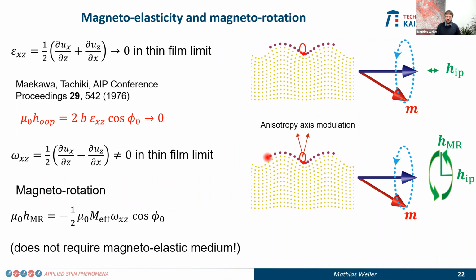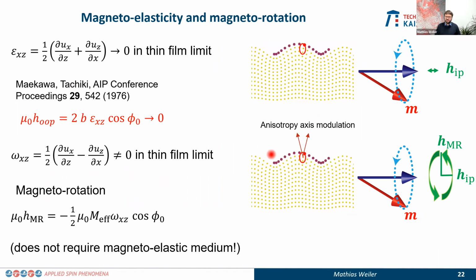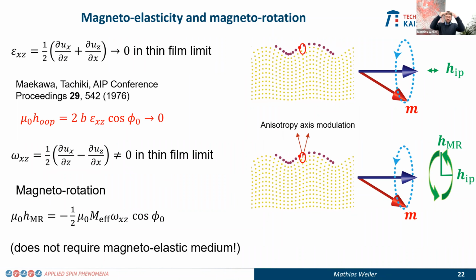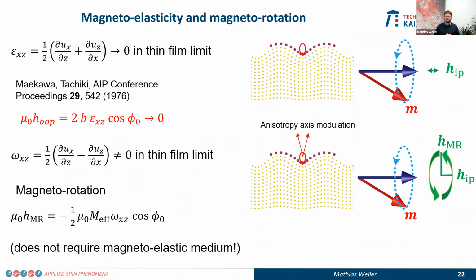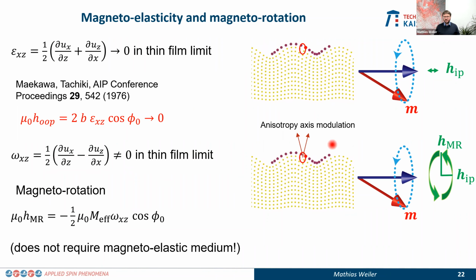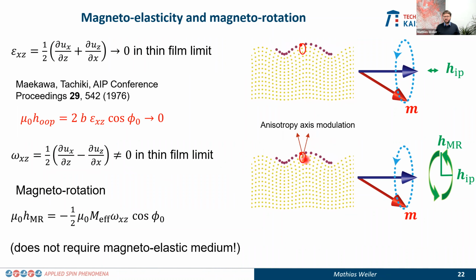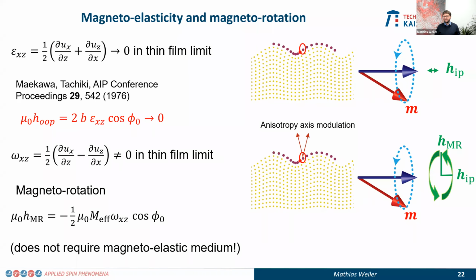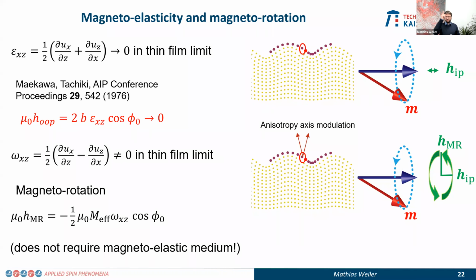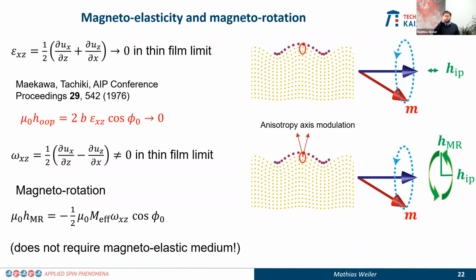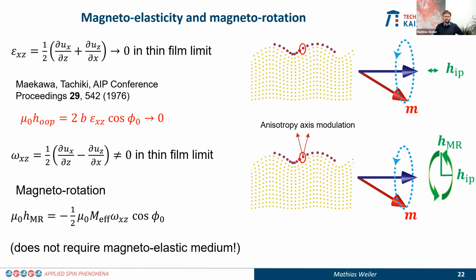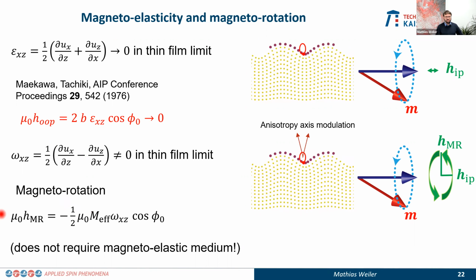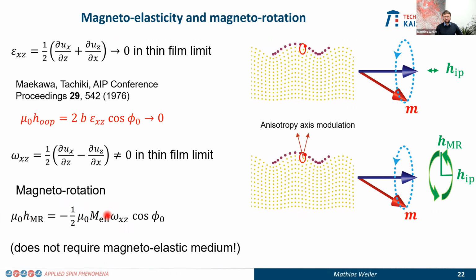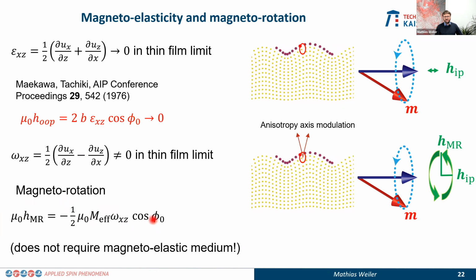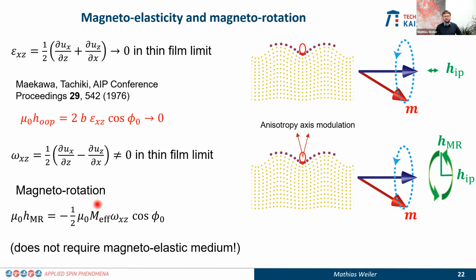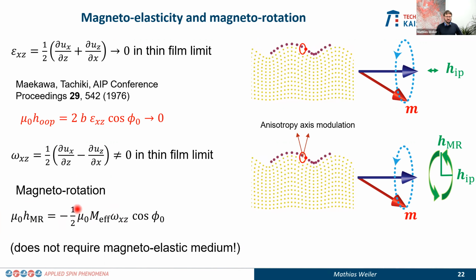And in magneto-rotation, you can now imagine that there is an interaction with the ferromagnetic thin film, because what it does is it's basically like bending the thin film of the ferromagnet. And if this is a hard axis ferromagnet, as we typically have, easy plane hard axis ferromagnet, in-plane magnetized, it means you're basically modulating the anisotropy axis direction with the frequency of the acoustic wave. Okay? And that's also why this magneto-rotation field contains the strength of the anisotropy field, which for a thin film limit is just saturation magnetization divided by 2. Okay, and that's what's in here.